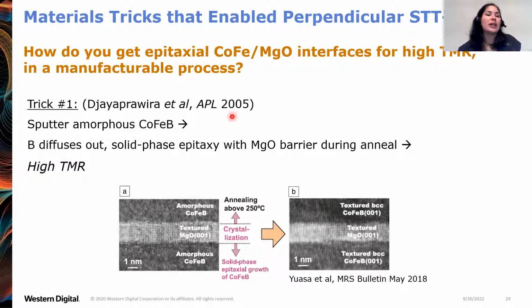So this trick here was published in Applied Physics Letters in 2005. And what we do is we start out with a cobalt iron electrode, but we make it amorphous by alloying in boron, 20 to 30% boron. And then we do a sputter deposition of the MgO tunnel barrier onto the amorphous surface of the cobalt iron boron electrode. So fortunately for us, when the MgO, which has a rock salt crystal structure, is deposited on an amorphous surface, it takes the desired crystallographic orientation that we want, this 001 orientation.